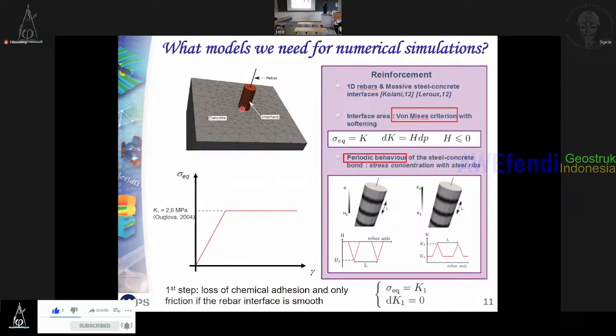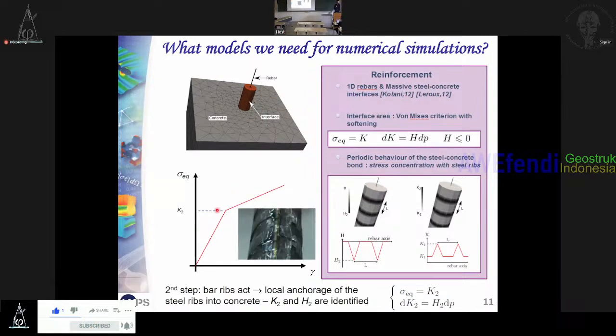The simplest law that we can use to represent sliding is an elastoplastic law. You have a linear part here, and after you have this plastic part. But if you look in detail at the rebar, as Dirk Schlicker said before, you have ribs. In order to be more representative of the effect of ribs, the idea here was to change the parameters between ribs. The behavior is quite complicated because between ribs you may have compression of this part, and it will increase the performance of the interface. And also you increase the contact surface between rebar and concrete because of the ribs.